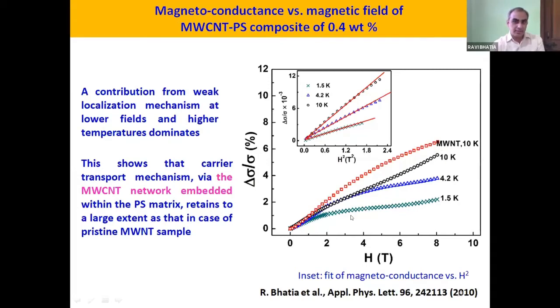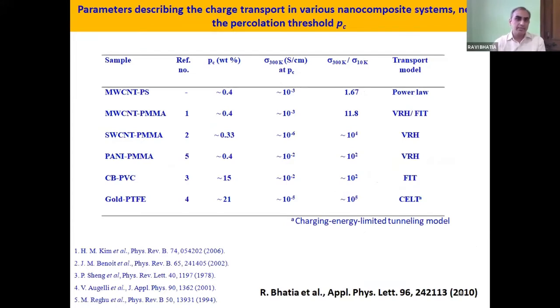MWCNT, and this red curve shows the magnetoconductance of MWCNT. That means all these curves are in the same scenario, showing positive magnetoconductance, that is negative magnetoresistance. It means that a very important thing is that the properties of multi-wall carbon nanotubes are still retained within the composite material. Hence, the results are validated, and finally we can look at it again in terms of the tabulated values.